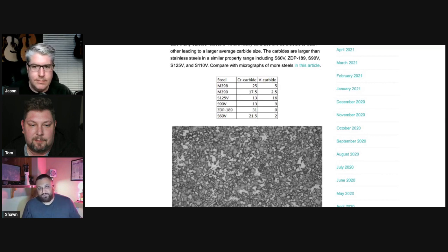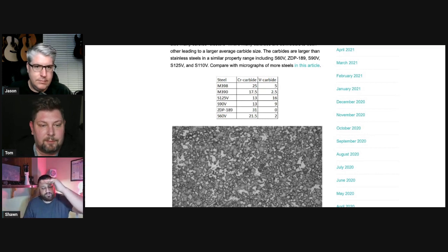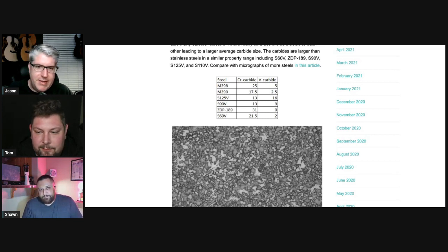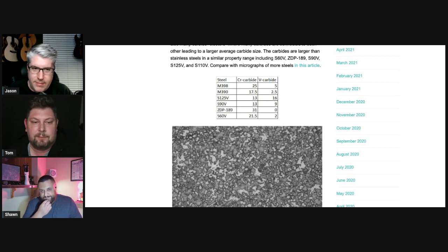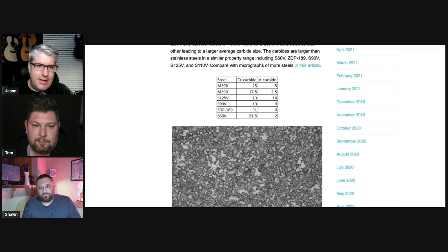Carbides have hardnesses to them depending on the chemistry of the steel. The carbides will have a chemistry. Vanadium carbides are always going to be significantly harder than chromium carbides. If we could pause for a minute, please, for the benefit of the audience, guys. When we talk about carbides, you might think carbide means carbon. Carbide really, to me, means anything that's added to the steel that's not necessarily iron, with the purpose of making the edge. It's a mixture of metallic element and carbon. Right.